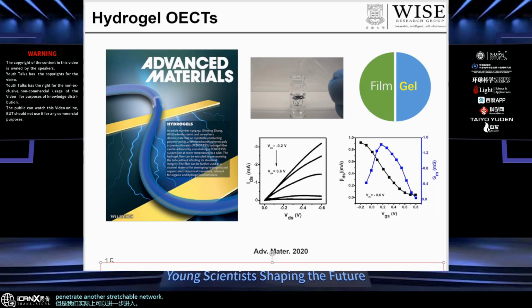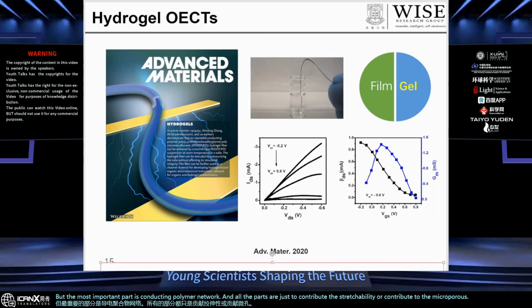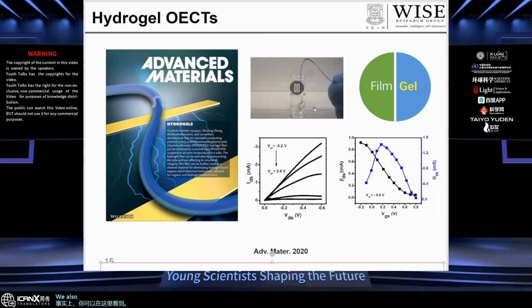But then we can further penetrate another stretchable network, for example polyacrylamide or other kinds of stretchable networks, to form an interpenetrated network. Sometimes you may also want to use, for example, sodium alginate. In our case, I think we have a triple network. But the most important part is the conducting polymer network, and all the other parts just contribute stretchability or micropores in that film. You can see here that we also cannot make them too thick. For example, here we make them fiber-like, with a diameter of around 10 to 100 micrometers, and we found that it functions well.